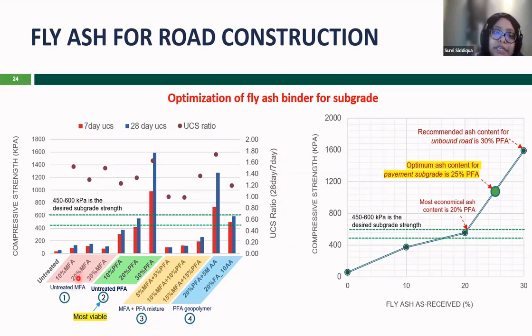So we have untreated fly ash. We have 3 different types of combination: 10%, 20%, and 30%. For this type of fly ash, you see that we have MFA and also PFA. So we have used both types of fly ash from the pulp industry, the multi-cyclone and the precipitator fly ash. The first one here is MFA, which is the multi-cyclone fly ash. Then the similar percentage of the precipitator fly ash without any treatment. So these are the untreated ones.